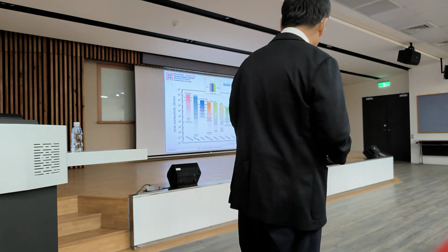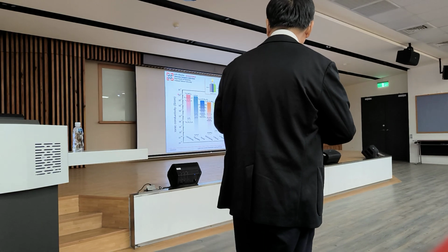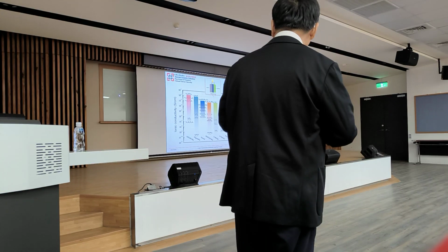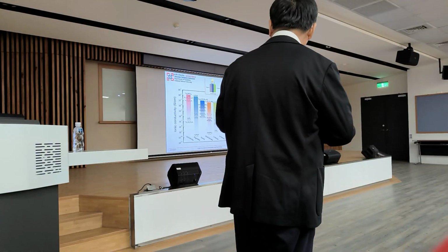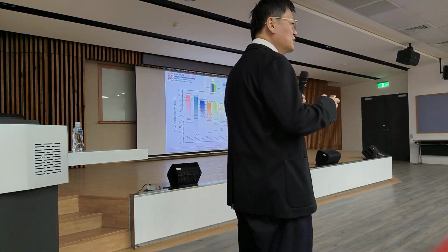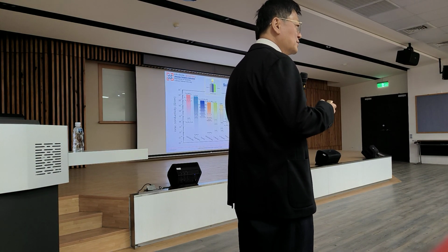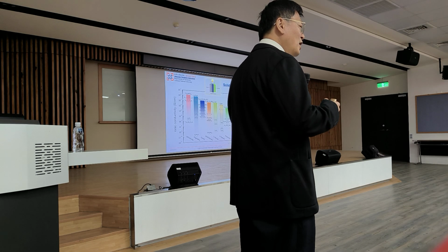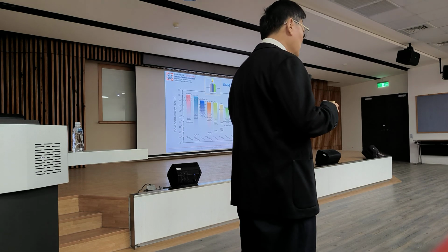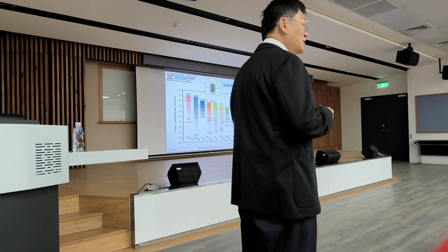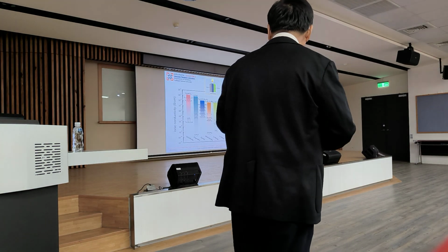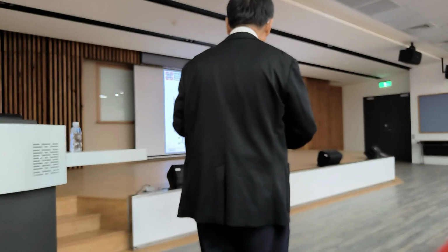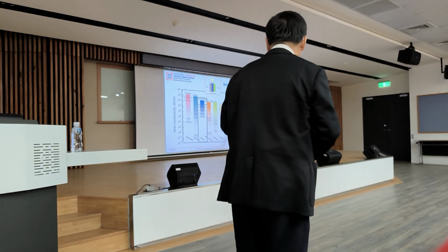What kind of material can do this? So you see the conventional liquid one has a conductivity up to 10 to the minus 2. But with sulfur content, it can reach this data. But sulfur is dangerous. When it explodes, it can release H2S. That's even more dangerous. So that's why this material is controlled by Toyota. Up to now, others cannot use it freely. For our study, we use oxide material. Okay? Even a little bit less conductive, but it's safer.